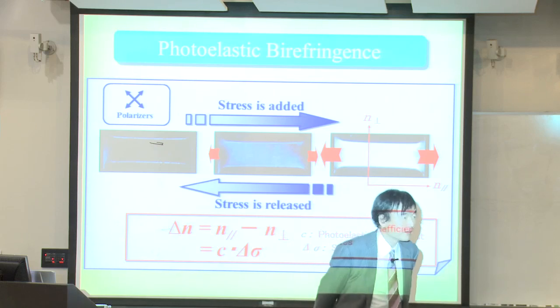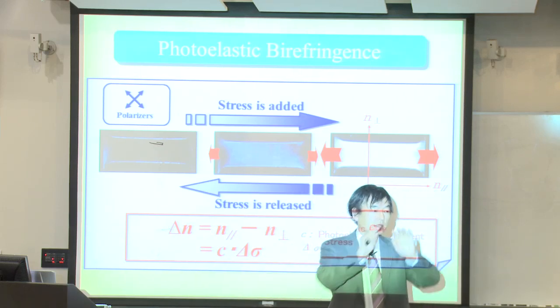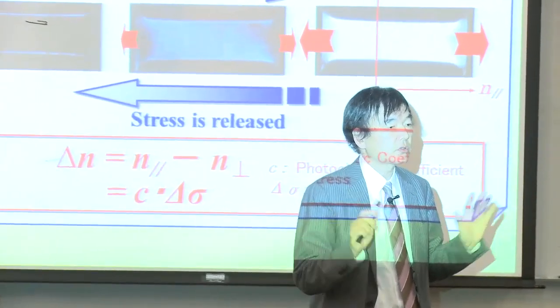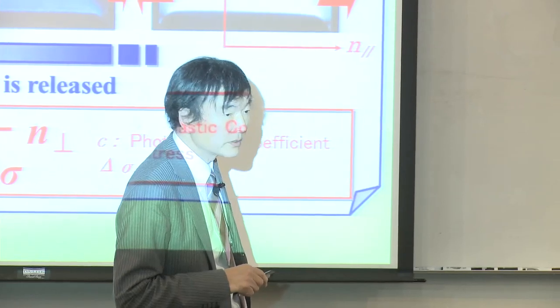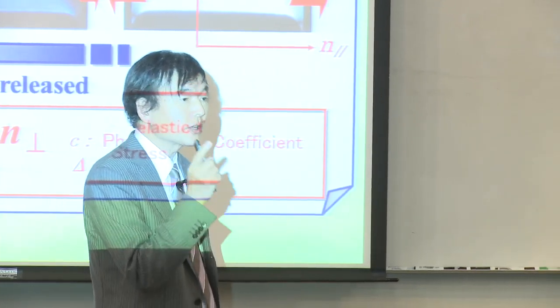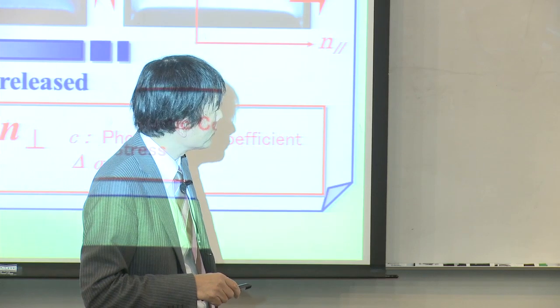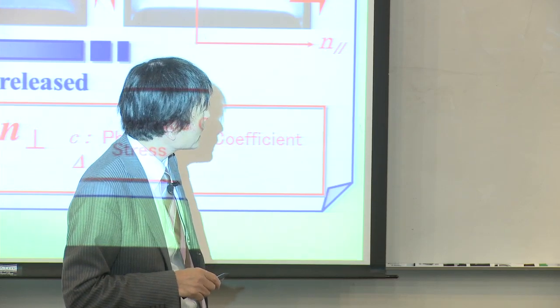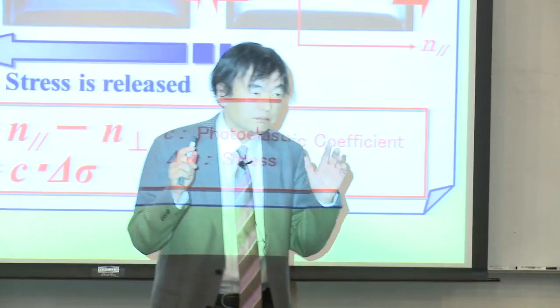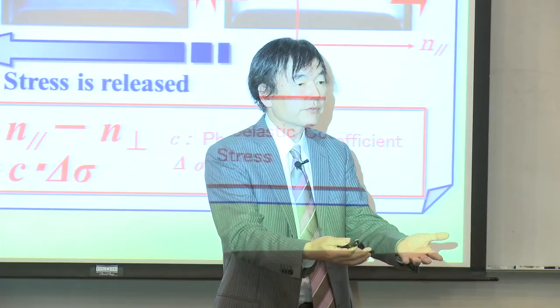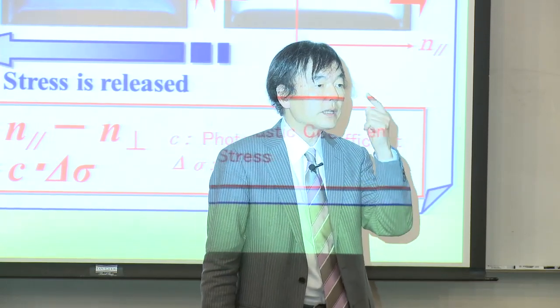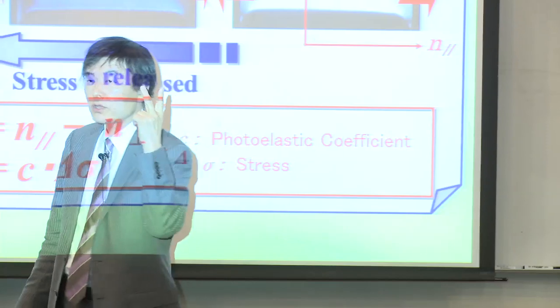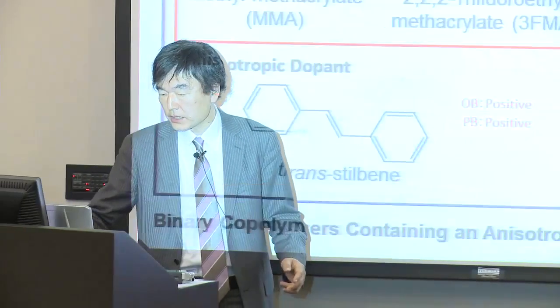Then I wrote the papers. Zero birefringence polymer, we succeeded in it. But with using this polymer film for a large screen display, the quality is not so good. This is a zero birefringence polymer with only orientational birefringence. If we add stress, serious birefringence is caused. Release the stress, it goes back to transparent. So this birefringence is caused by photoelastic birefringence. So in order to completely make a material zero birefringent, there are two mechanisms. One is the orientation of the polymer chain, and the other is photoelastic birefringence. So we have to cancel both.